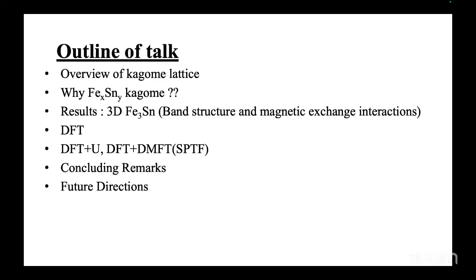And then I will discuss my core results of the 3D Fe3Sn system by analyzing the band structure and the magnetic exchange interactions that I got through the ab initio methods of DFT and also beyond DFT, going for DFT plus U and DMFT. Then I will summarize the concluding remarks and what can be the possible future direction based on the work that I did in this system.